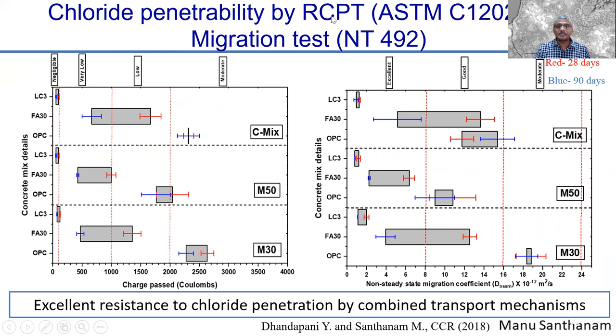So if you compare the results of a rapid chloride penetration test, RCPT, by ASTM C1202, you see here that the Portland cement mixes are always in this 2000 to 4000 region, irrespective of the type of concrete. Okay. The fly ash based mixes have now come down to around 1000. And of course, in fly ash, if you cure for 28 days and then cure for 90 days, the enhancement in the durability is significant. That means the longer you cure, the better the durability gets with fly ash mixes. With LC3 mixes, even with 28 days curing, you're already in this negligible chloride penetration range, less than 100. So you can see it's a dramatic effect as far as LC3 is concerned.